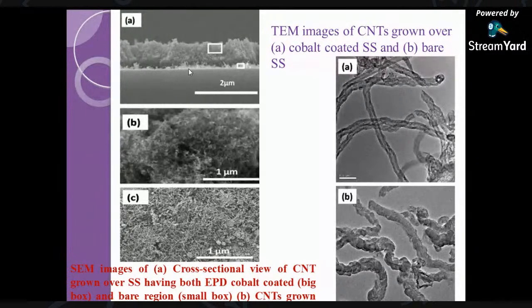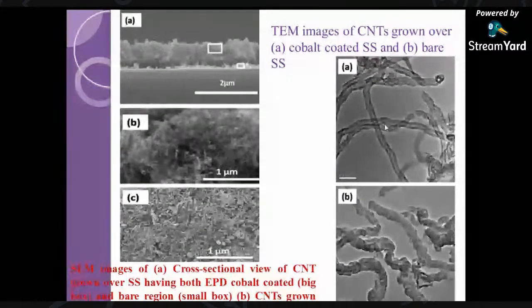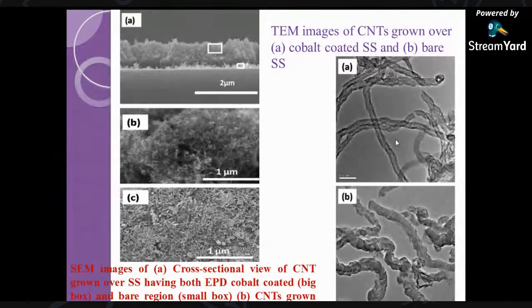This is a portion of a cross-sectional view of this stainless steel, which has carbon nanotubes from cobalt and from stainless steel. This gives you the picture of carbon nanotubes obtained from cobalt nanoparticles, and this is the carbon nanotubes that you get from bare stainless steel. This image shows a more clear view of these carbon nanotubes: carbon nanotubes from cobalt coated stainless steel, and this shows bare stainless steel. You can see the difference between the structures. The structure varies because of the cobalt and the absence of cobalt. The one with cobalt has a very beautiful multi-wall structure, and this is one of the common morphologies that you can find when you synthesize carbon nanotubes. Here you can see carbon nanotubes, but with a lot of defects in them.